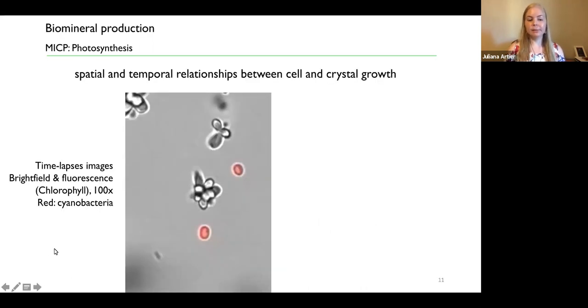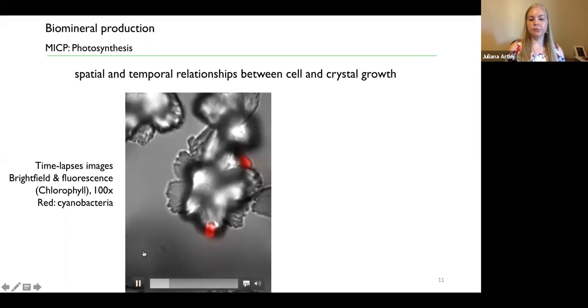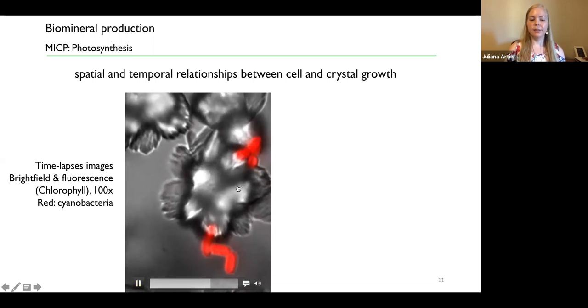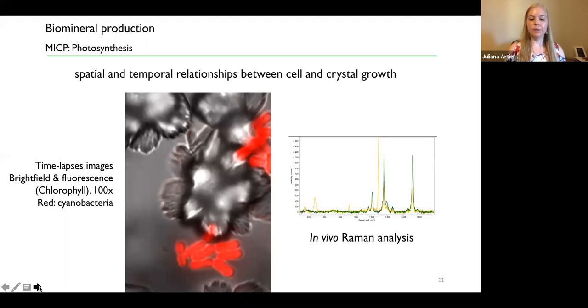So one of the things that we're doing in our lab to try to understand how the physiological state of the bacteria is involved with crystal production, we're using time-lapse microscopy so we can follow real-time formation of the crystals and how it affects the growth of the bacteria. And if we leave these crystals to grow further later, we can see them forming structures like we saw in the SEM first. By using quantitative MATLAB protocols that we have previously established, we can follow the growth of the bacteria and how it's affecting its physiological state. And we can combine this with traditional Raman analysis to understand what kind of polymorphs are being produced by the bacteria. So we are trying to understand a little bit more about how the photosynthetic process is working in the MICP production.